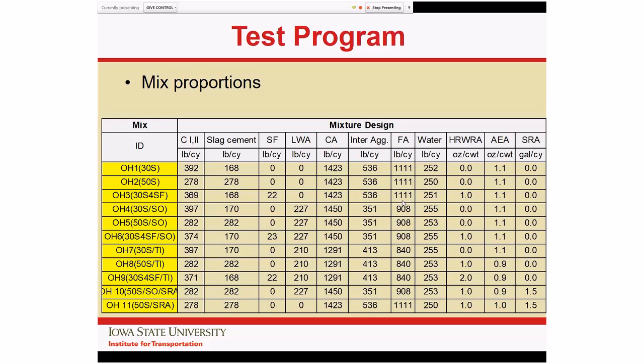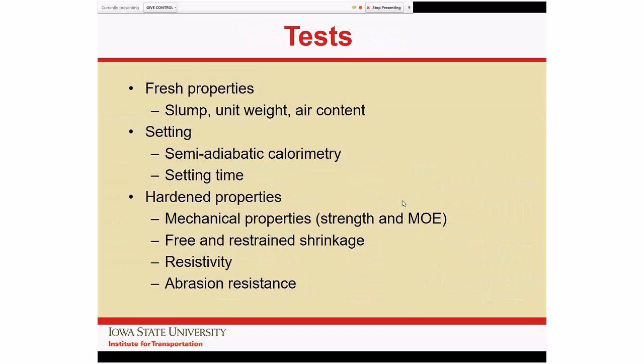Now, I'm not going to chew on this one a whole lot, just to say we produced 11 mixtures with different dosages of slag, SRAs, and the 2 different lightweight fine materials that we played with. For the properties that we measured, the fresh properties were slump, of course, the unit weight and the air content. We measured setting time using calorimetric approaches and conventional pin-based devices. For the hardened properties, we looked at strength, modulus of elasticity, and shrinkage, both the free test and the shrinkage ring. We also measured resistivity as an approach of assessing the permeability. So again, the better the resistivity, the longer the system is going to last. We also did a little bit of work looking at abrasion resistance.